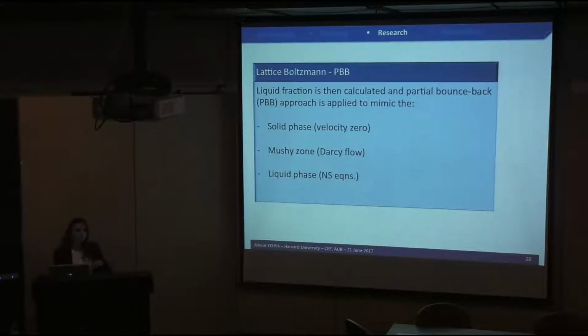But of course, when we're dealing with a phase change, there are at least three phases. We have the solid phase, the mushy zone, and the liquid phase. What is helpful about lattice Boltzmann is that we can use what is called the bounce-back rule. This bounce-back can block the fluid flow in the solid phase to render the velocities equal to 0. It can partially bounce back in the mushy zone according to a certain liquid fraction to partially allow the fluid flow, and that's why we treat this mushy zone as a flow in a porous medium,